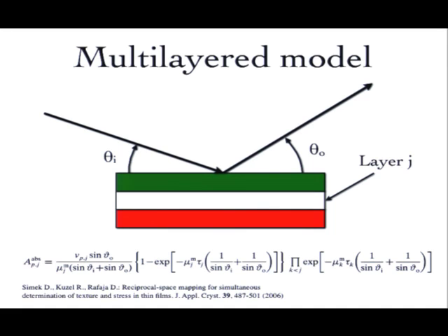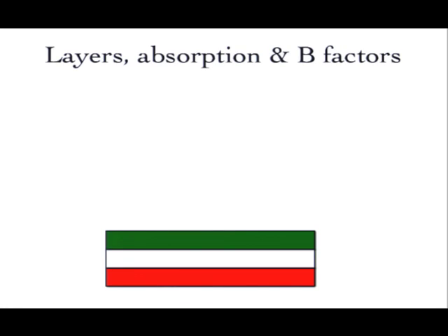So there is this nice formula, which I'm now using in my program, as it's very nice because you don't deal with any tilting, etc. You only need to put the inclination of the incoming beam and outgoing beam, okay? And then there you have the absorption for the phase P in the layer J. Okay, and this is easily computable if you have the composition of the phase.